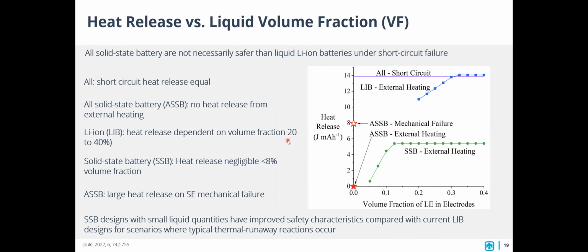So a recent report that came out of Sandia showed that even if you have one of these solid state batteries that replaces the liquid electrolyte, if you short the system, the heat release essentially will be the same in your battery. But if you have a mechanical failure of your battery or external heating of your battery, then the heat release from the system will be minimized by moving to an all solid state battery.